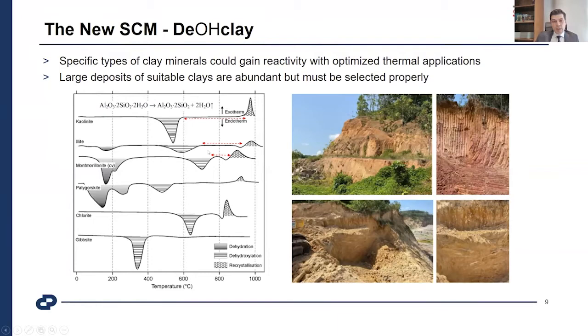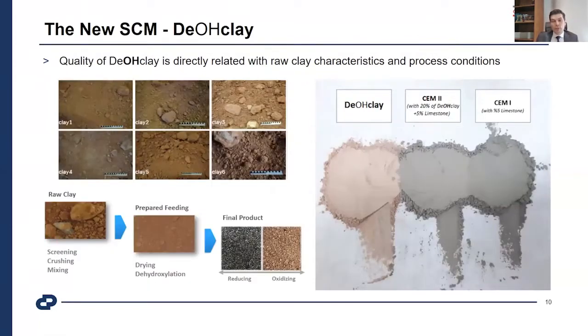And second, illite can be used, as you can see here. Montmorillonite can also be used, but its disadvantage is the range between the endothermic dehydroxylation part and the exothermic recrystallization part. The temperature range is very narrow and not easy to control. If a high amount of montmorillonite is present, there's a risk of causing recrystallization or non-dehydroxylated parts. Because of that, we focused firstly on kaolinite and then illite compositions in the reserve surveys.